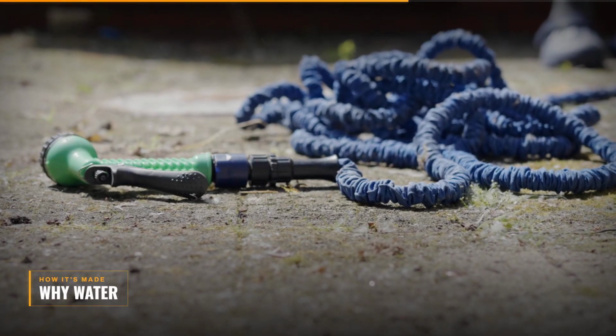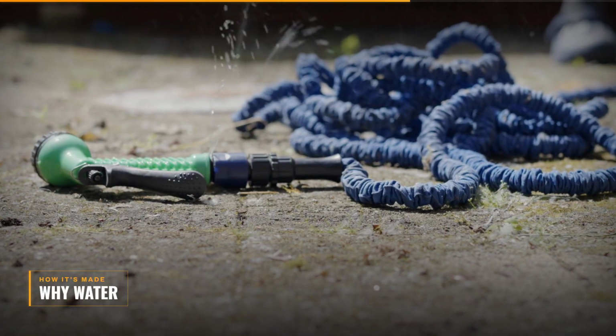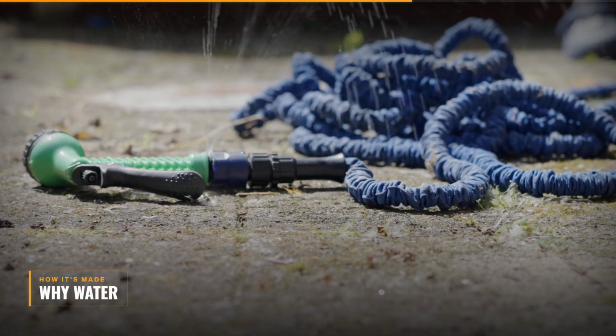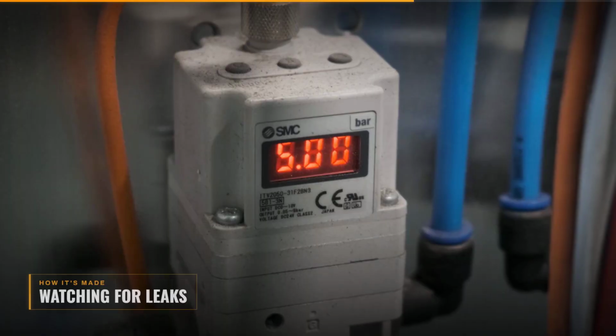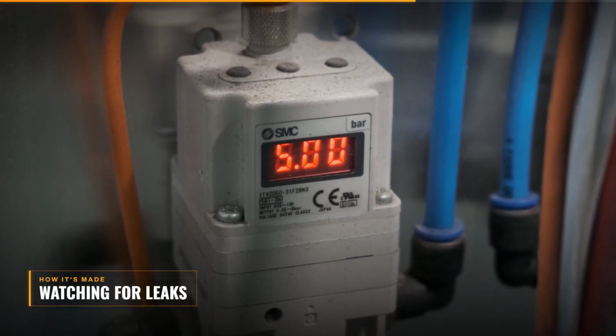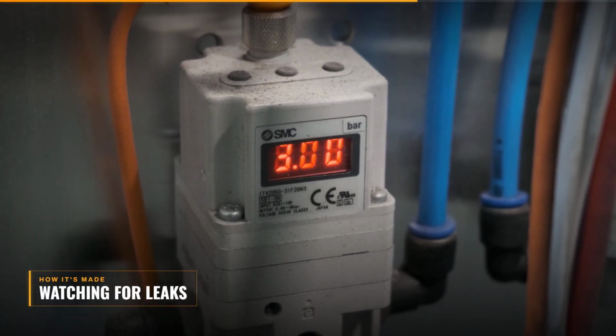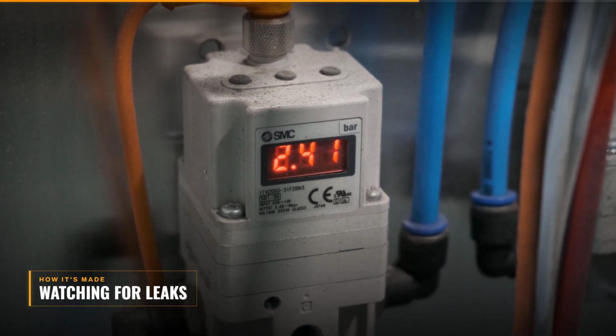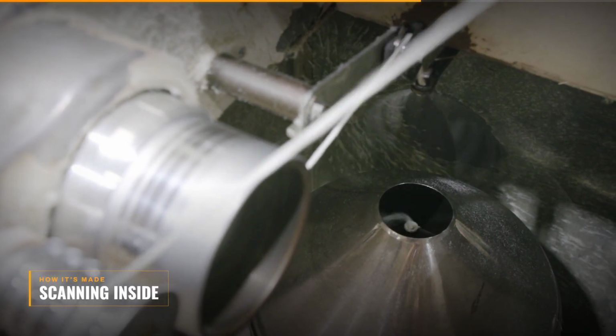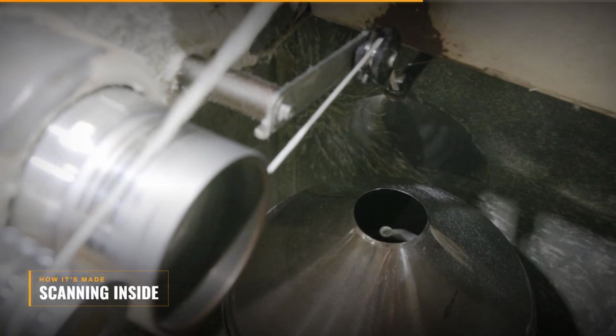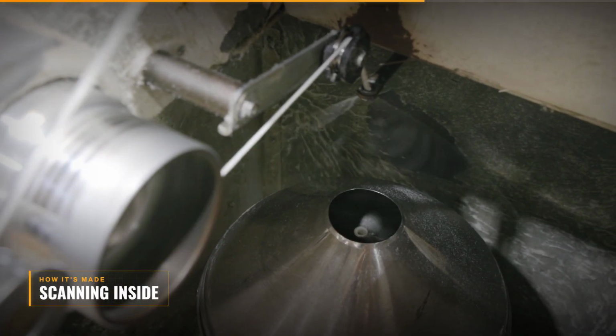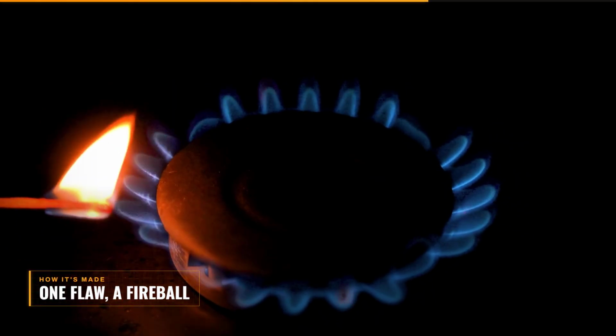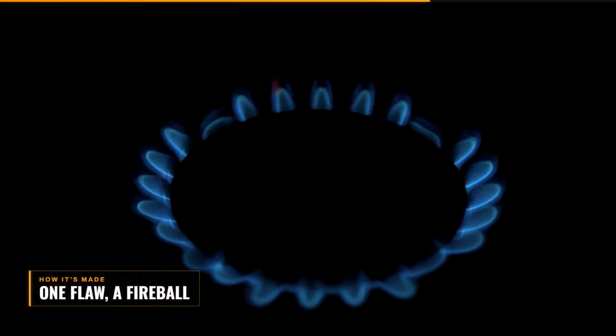Water is used because it barely compresses. If the pipe bursts, it does not violently explode. The pressure is held, while sensitive machines watch for the tiniest drop, the smallest leak. Then scanners sweep the walls with ultrasound, hunting for cracks hidden deep inside the metal. Because in a gas line, one single missed flaw can one day become a fireball.